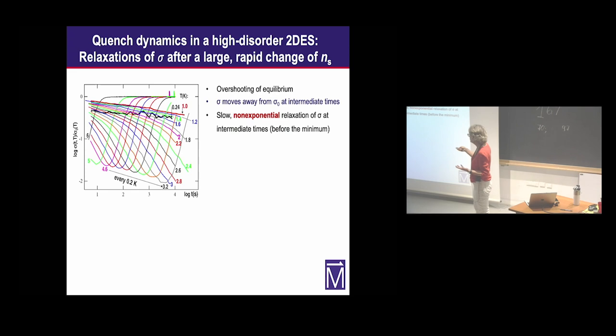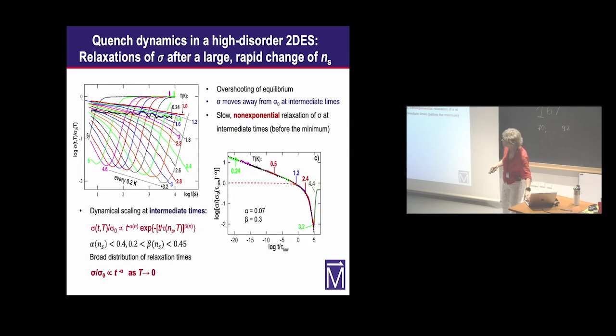As you reduce the temperature, this minimum shifts to longer and longer times until it falls out of our experimental time window. Now if we focus on what happens at these intermediate times before the minimum, we can see that this is not an exponential relaxation. In fact, we are able to collapse all of these curves onto the same curve and show that they can be described by this function, which is a product of a power law and a stretched exponential. In the zero temperature limit, this reduces to a pure power law. So it seems, based on this, that at zero temperature, strictly speaking, we have a glass transition.